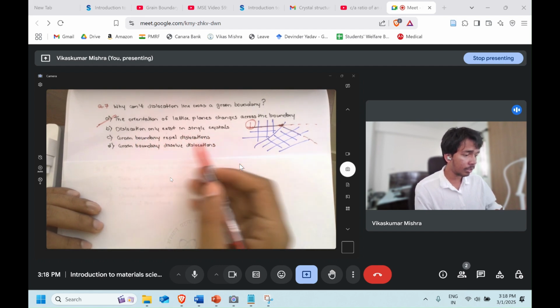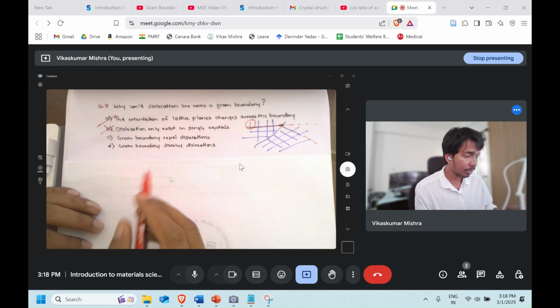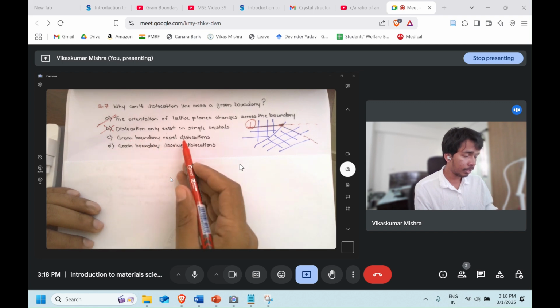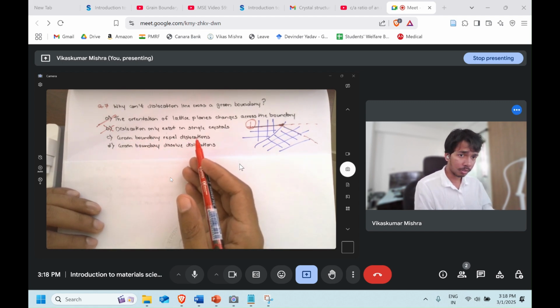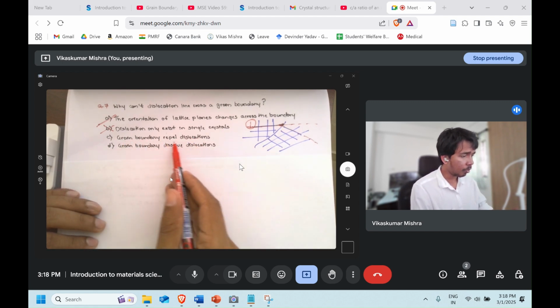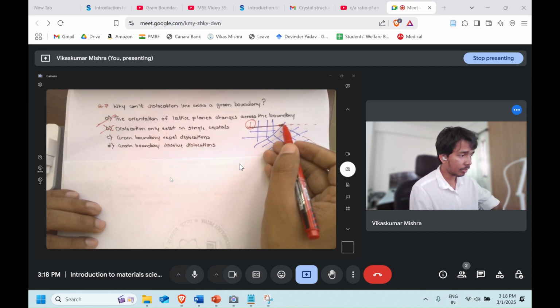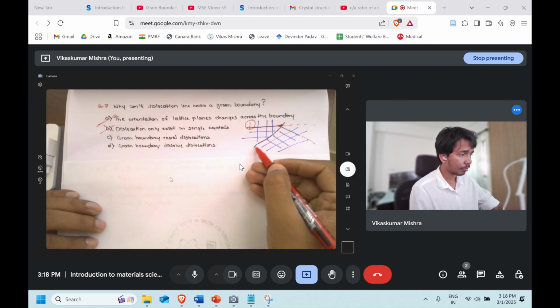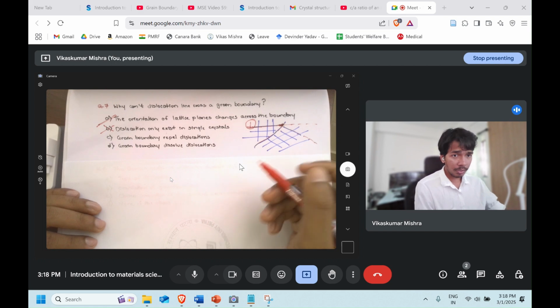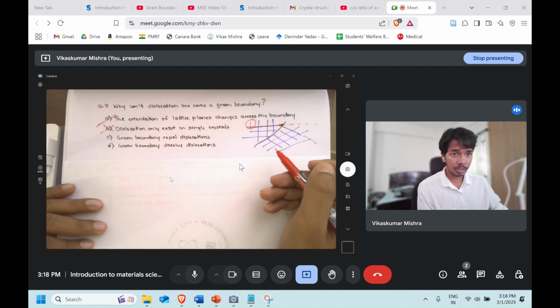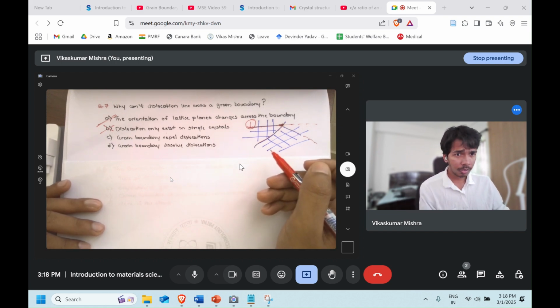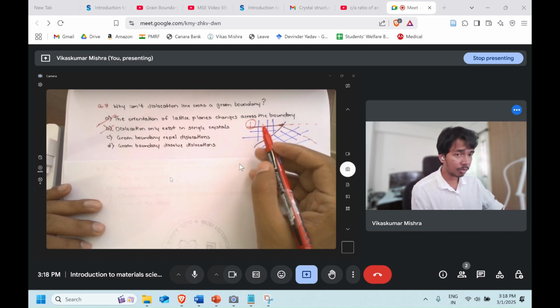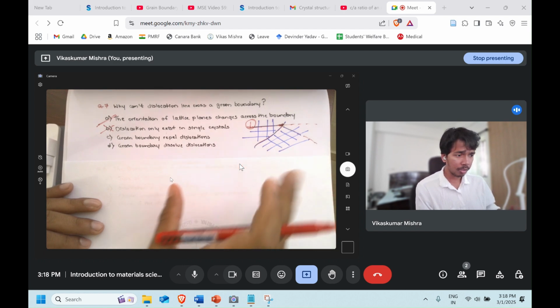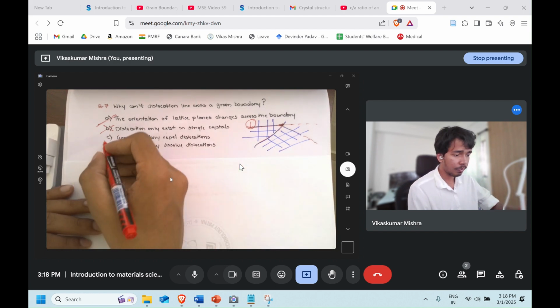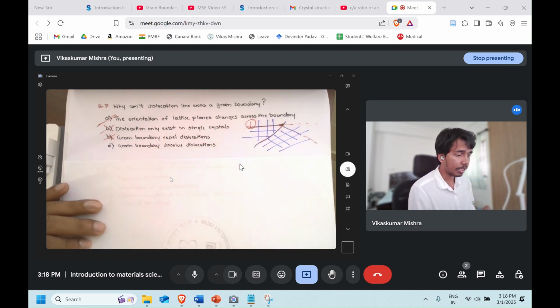Dislocation only exists in the single crystal: absolutely incorrect. Dislocation exists in the single crystal as well as the polycrystal. Grain boundary repels dislocation. Is it the case? No. Even if it is the case, let's say the grain boundary is repelling the dislocation, still multiple dislocation pile-ups can occur and they can break it. So this is not the primary reason. We'll say that it's incorrect.